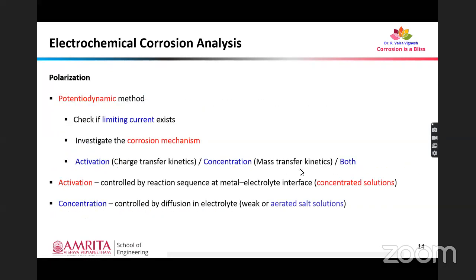So this potentiodynamic polarization method will give us the data on the existence of limiting current in the material, and it will help us in investigating the corrosion mechanism that is characteristic of the material that we have chosen. And we could analyze whether the corrosion mechanism takes place through activation or concentration based kinetics.